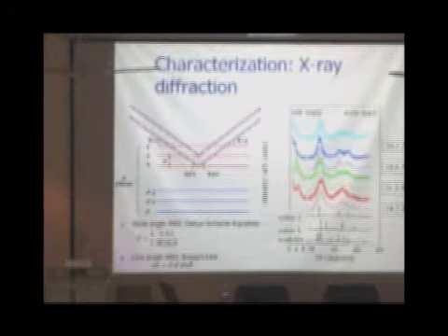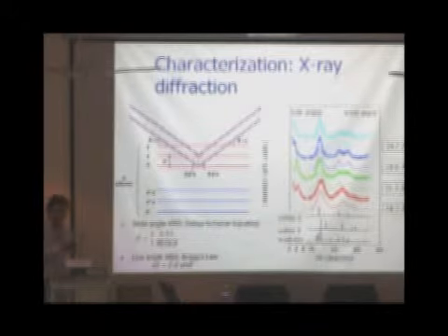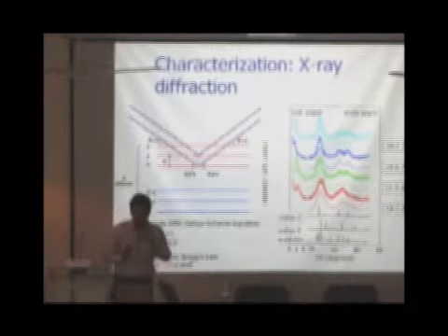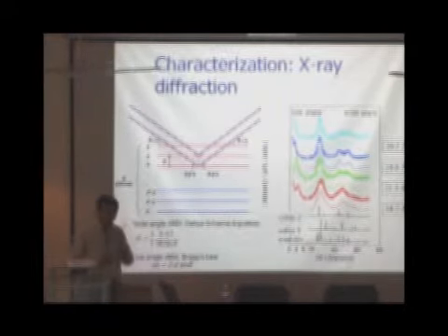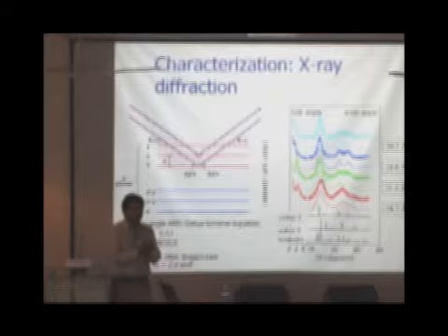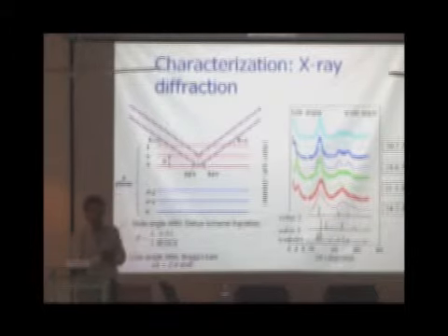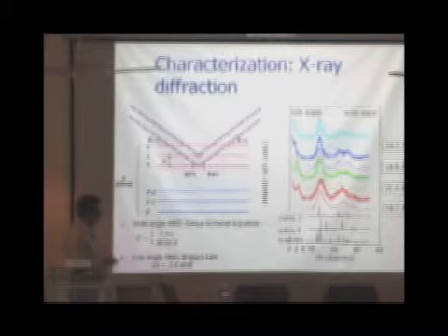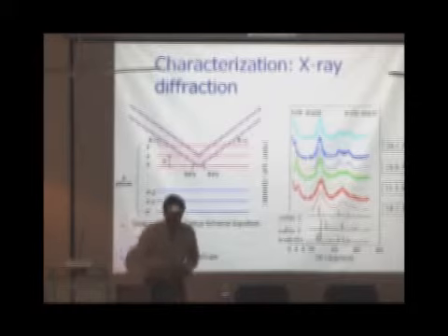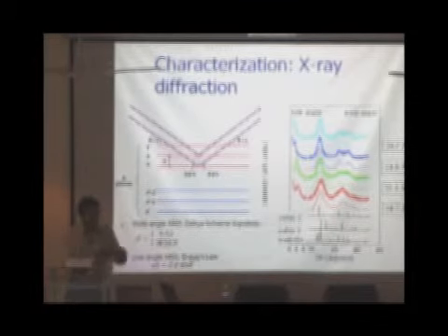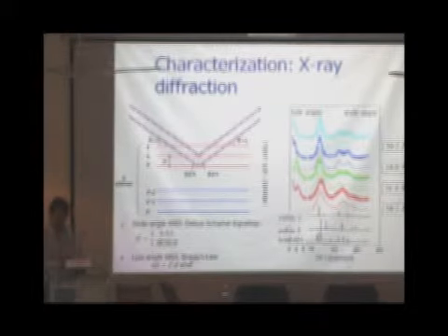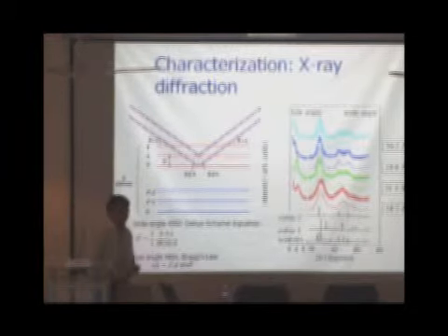If you do an X-ray diffraction experiment, there's something called the Scherrer equation, from which you can get the size of the nanoparticles, or the nanocrystals to be exact. I should be more careful using the word nanocrystals, because the X-ray diffraction size that you get is only for the crystalline part. And if Professor Mehta is angry with me one of these days, I just don't go to the TEM, I go to the X-ray diffraction and immediately get the size of the particles. But normally he's in a good mood.